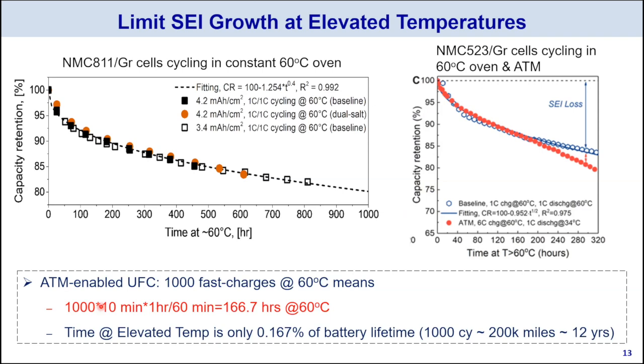Now, how much time do we actually stay at 60 degrees C in our operation? Let's say we do 1,000 fast charge cycles, and each cycle has 10 minutes. So total time is 167 hours throughout the lifetime, and that time at elevated temperature is only a tiny fraction of battery lifetime. If I plot that ATM time at 60 degrees Celsius over these two plots, you can see the resulting capacity retention is still well above the 80% limit.